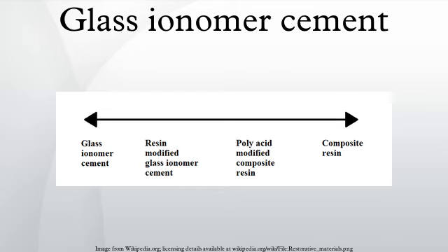The cross-linked phase becomes hydrated over time with the same water used for mixing. This process is called maturation. The unreacted portion of the glass particles is sheathed by a silica gel that develops during the removal of cations from the surface of the particles. Thus the set cement contains an agglomeration of unreacted powder particles surrounded by a silica gel in an amorphous matrix of hydrated calcium and aluminum polysalts.